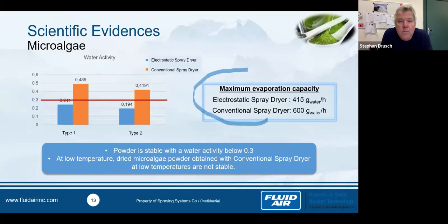So I said that we work at 90 degrees C of inlet temperature, but we change a little bit the flow rate and the gas inlet. So that means that we need 30% less energy working with the electrostatic spray dryer compared to the conventional spray dryer. Even if we decrease the energy needed to dry, we obtain lower water activity. So it's really great information.